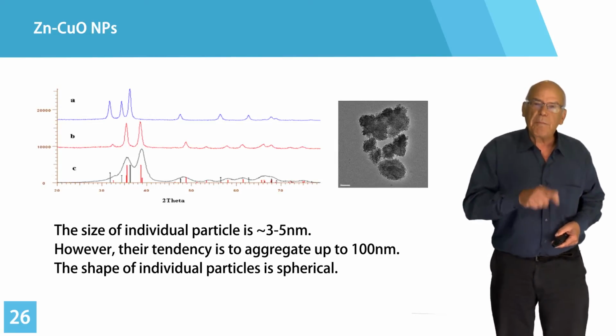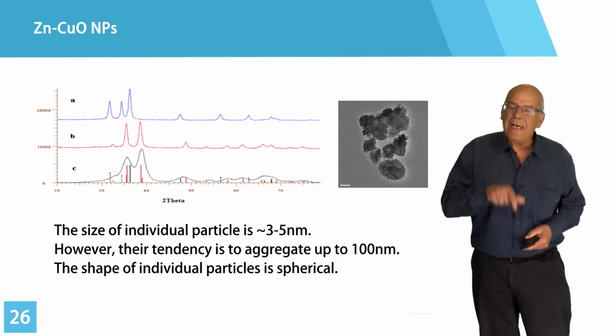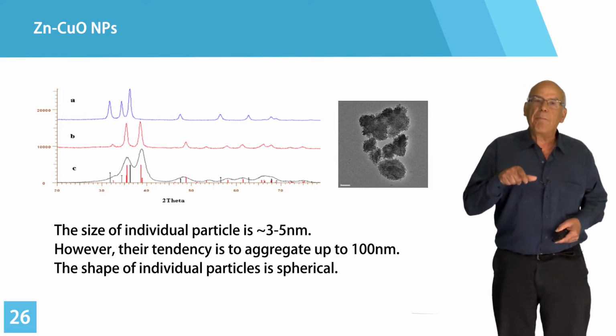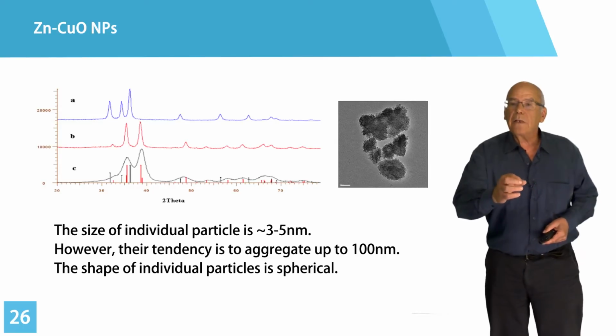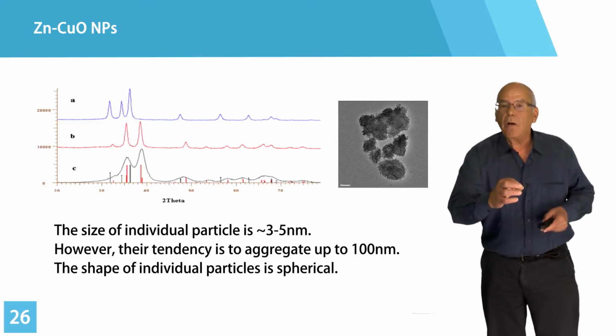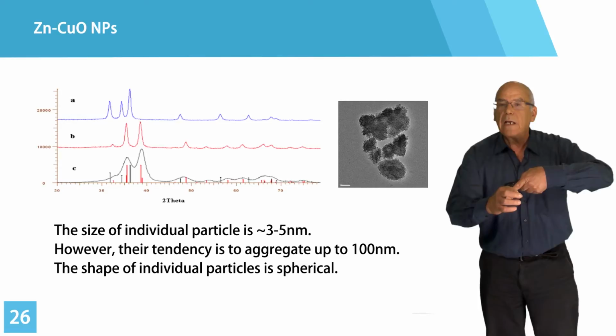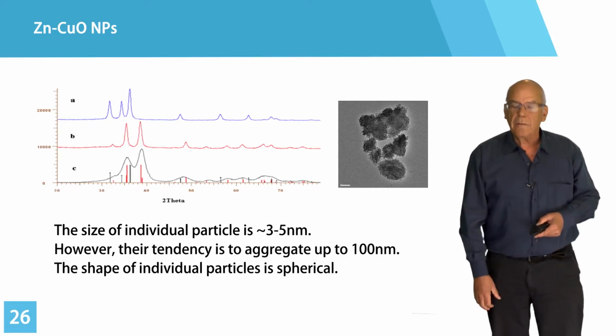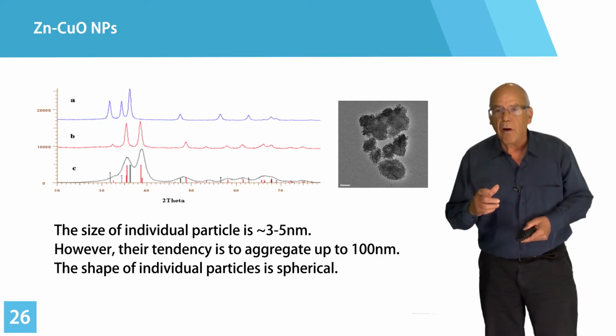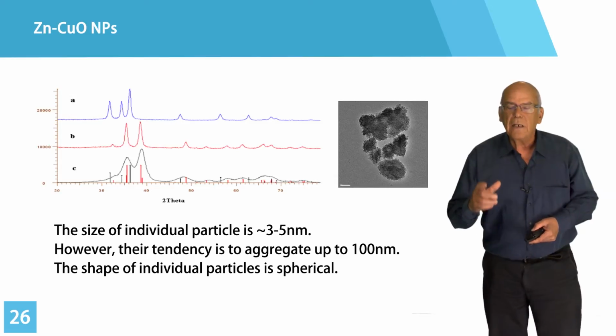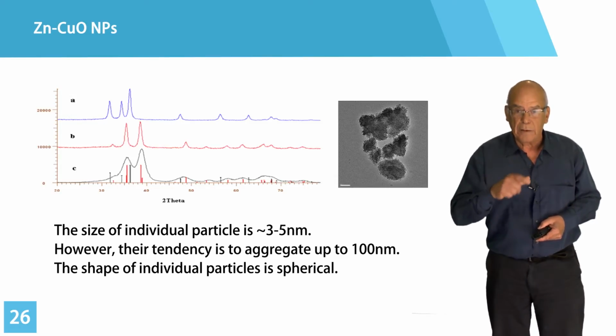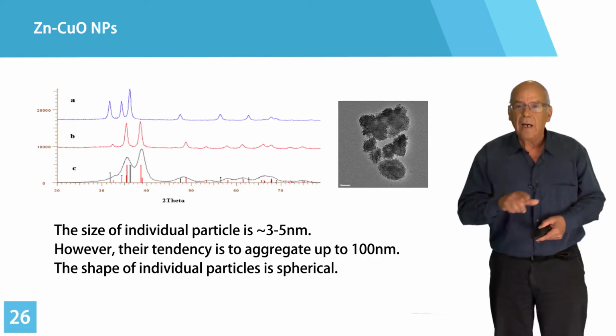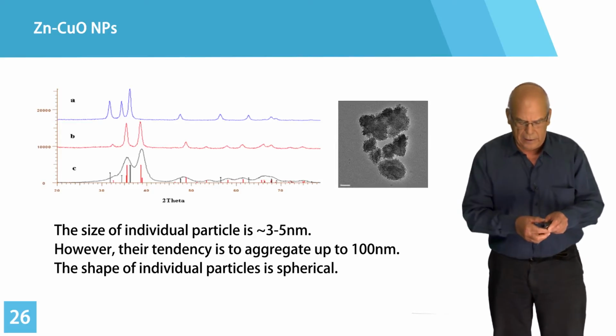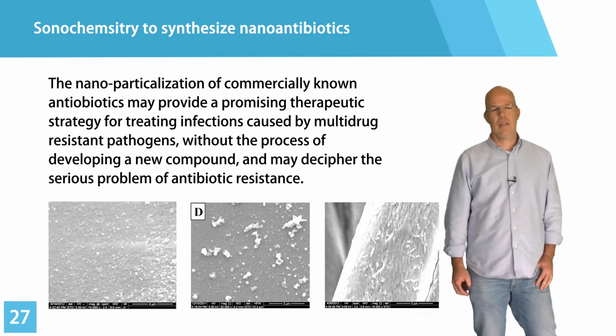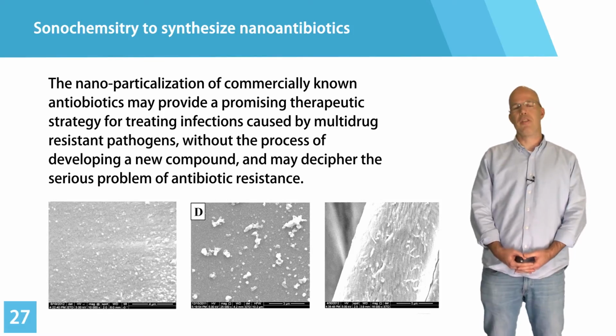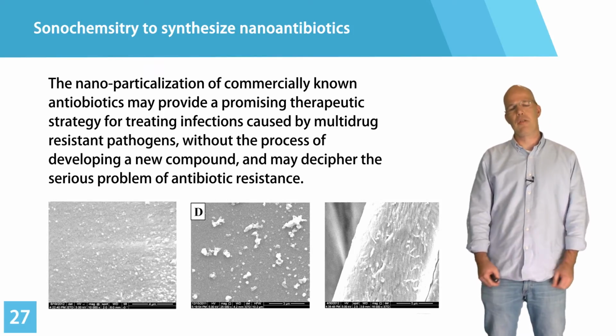And this shift means that we indeed perturb the unit cell of the copper oxide by introducing zinc ions into it. And as I mentioned before, the activity as far as killing bacteria is dramatically increased. Okay. So our second approach is actually again utilizing sonochemistry.